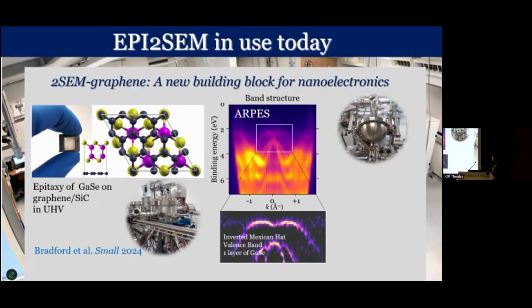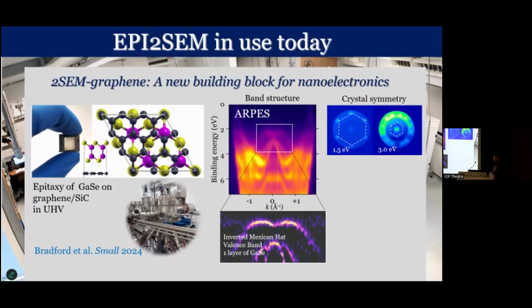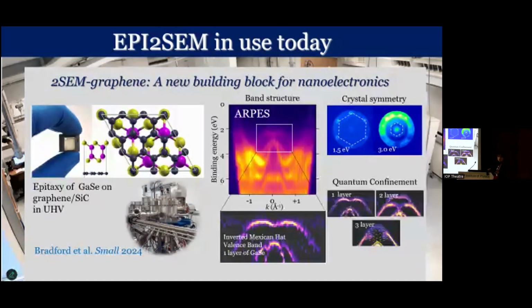And Van Hove singularity in the density of states, they are so important, for example, to then explore electron correlation effect. And we can look at the symmetry. We can understand how the two layers align relatively to each other by looking at the energy surfaces and explore how this band structure changes as we go from single to multiple layers. So we really have control now of this nanoscale system with atomic resolution.